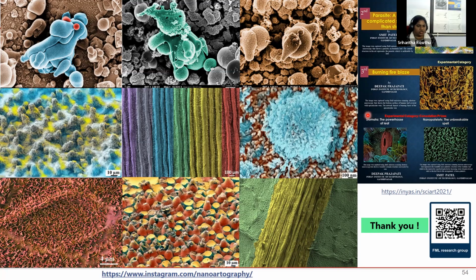Yeah, I got it. So for the quantification, what you can do is simply take a fully agglomerated slurry, which means you're not going to do any of these steps at all. You simply pour your powder into your solution and look at the solution with the DLS, dynamic light scattering experiment. Then you're going to get a bimodal distribution of the particles. Why? Because your smaller particles are going to show up as one single peak, and your bigger agglomerates are going to show up as a second peak at the right side on your x-axis.